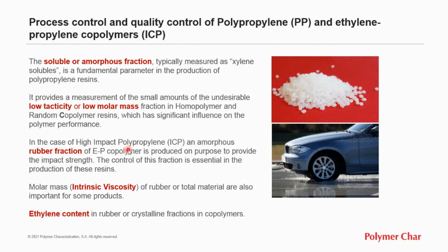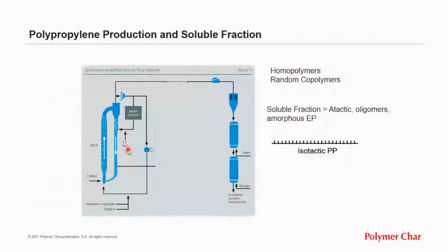In the case of high-impact polypropylene, an amorphous rubber phase is produced on purpose to give impact strength, and the control of that fraction is essential also in the production of those resins. The molar mass through the intrinsic viscosity of the rubber and total material are also important for some products, as well as the ethylene content in the rubber phase or in the crystalline fractions in copolymers.